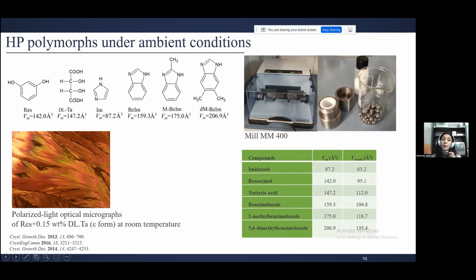So I mixed tartaric acid with the resorcinol in different percentages, for example, 5, 15, and 25, because they also used different percentages. When we checked how they did the experiment, they mixed these 2 compounds, dopant and host, and melted it. And after cooling down, they did powder diffraction. And by checking the powder diffraction, they noticed what the phase is. So after that, we also checked it, and it was the same result.